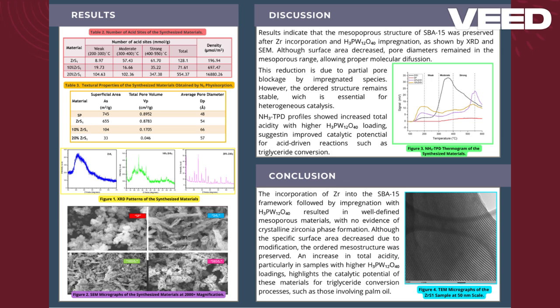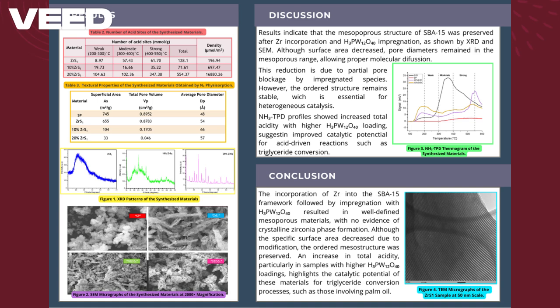Conclusions. The incorporation of Zr into the SBA-15 framework followed by impregnation with heteropolyacid resulted in well-defined mesoporous materials, with no evidence of crystalline zirconia phase formation. Although the specific surface area decreased due to modification, the ordered mesostructure was preserved. The increase in total acidity, particularly in samples with higher phosphotungstic acid loadings, highlights the catalytic potential of these materials for triglyceride conversion processes, such as those involving palm oil, offering an efficient and sustainable route for the production of clean fuels from this oil.